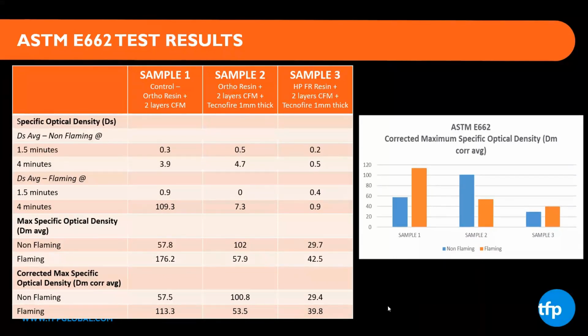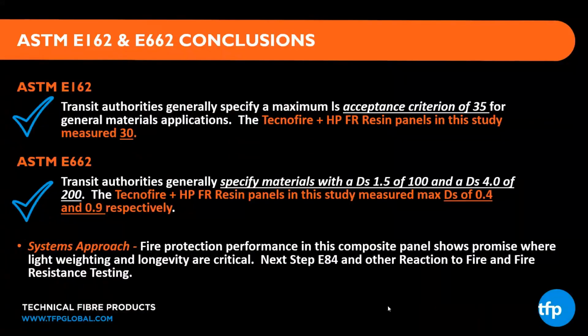Next slide, please, Neil. I'll summarize both these tests on this slide. So the ASTM E162 panel test that we ran, transit authorities will look at an acceptance criterion of 35 for this flame spread. The Tecnofire plus the high performance resin panels measured a 30. So we would have qualified for that, which also would have qualified for the DOT-90 in terms of a design.